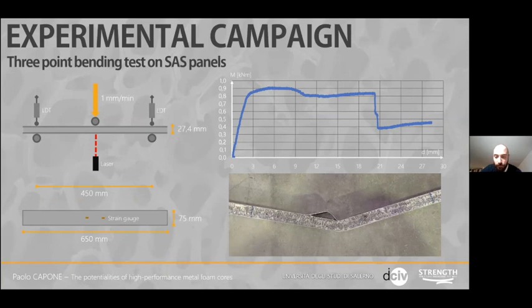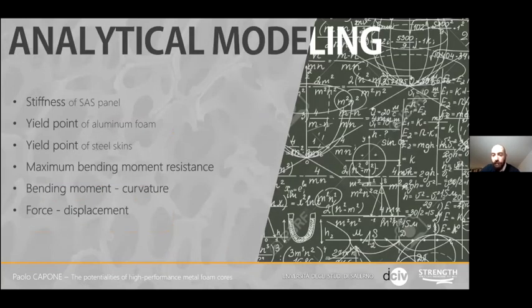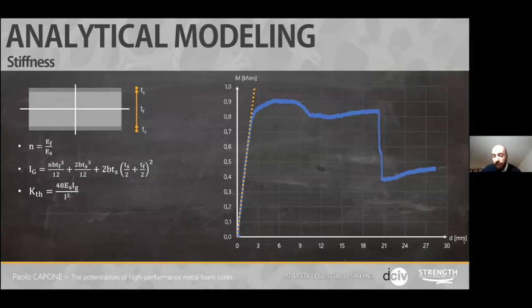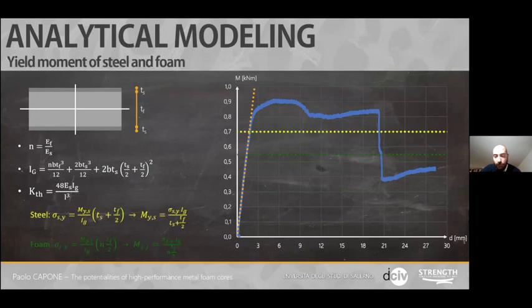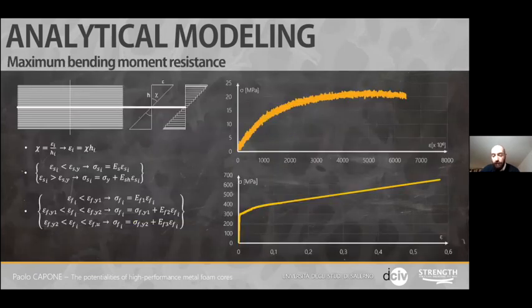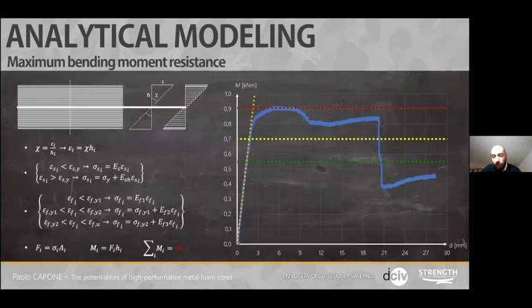Then an analytical modeling phase has been performed, adopting simple elastic and plastic modeling approaches to predict strength and stiffness. And here follows a quick presentation of the results, starting with the stiffness of those SAS panels and then the yield strength for both steel and foam of the sandwich panel. Then, using the stress strain curve for steel and foam, the maximum bending moment resistance has been calculated.